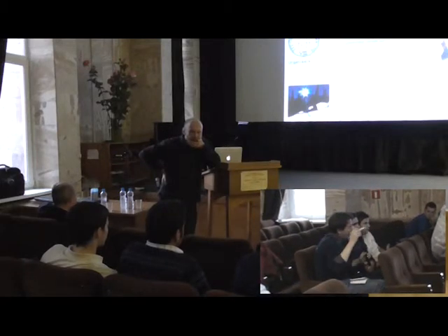Perhaps it's the same. At the beginning, you have shown that you simulated this knock-out of atoms due to electrons, right? Yes, knock-on damage. But you don't actually simulate the electrons coming, right? No. You give kinetic energy to the atom, something like that, right? Yes, because the transfer of energy to the nuclei occurs on the attosecond time scale, 10 to minus 18. It's basically an instantaneous transfer of kinetic energy, and then the atom starts moving slowly. As I mentioned already, it's like a very speedy, energetic bullet hitting a big, heavy ball, and then the ball starts moving.